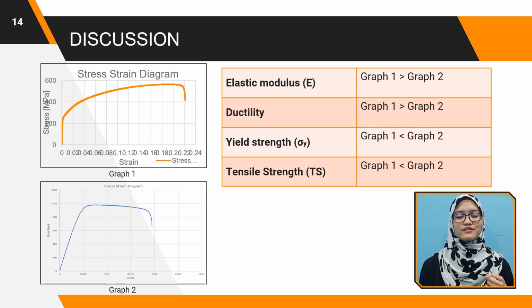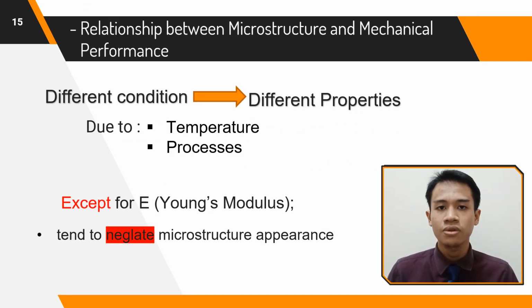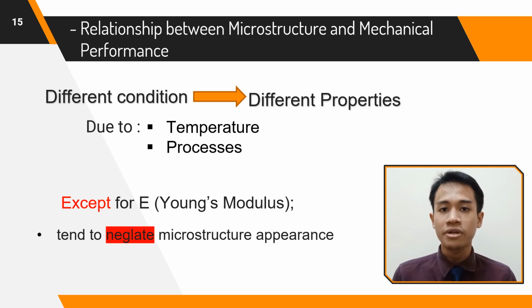From this, we can observe the different tensile properties between these two graphs, which graph 1 has higher elastic modulus than graph 2, and graph 1 is more ductile than graph 2, while graph 1 has lower yield strength and tensile strength than graph 2. By analyzing the experimental results, different conditions of the same materials lead to different tensile properties due to certain processes or temperature. In general, the performance of the alloy, including tensile properties, is mainly dominated by the microstructural features, except for Young's modulus, since it tends to neglect microstructural features.